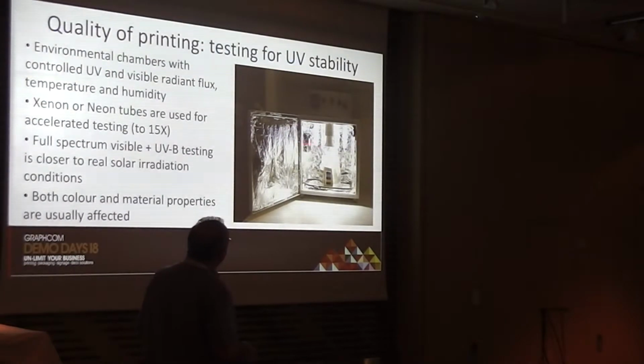And there's a little chamber that we use for very aggressive conditions. It actually has UV. It has extremely intense white light. It's so intense that you cannot put your hand there; you'll burn. And it's rotating. At the bottom, you can put in high temperatures. We can go up to 70 degrees. And we can feed it with seawater. So essentially, you cannot get more aggressive than that.